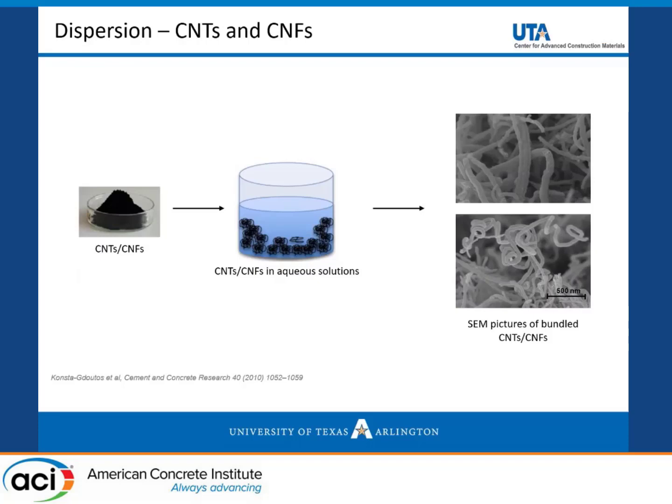One of the issues, when we use conventional fiber, we know that rheology and workability become important. It becomes even more important for graphene-based material because they have a huge surface area, and that means a high van der Waals force, so it is very difficult to disperse. If you do conventional mixing with fiber reinforced concrete, you get agglomeration.